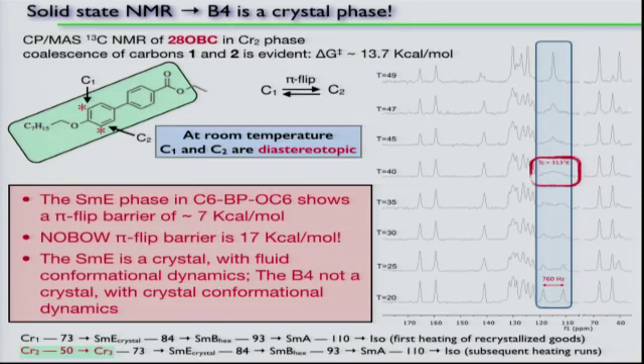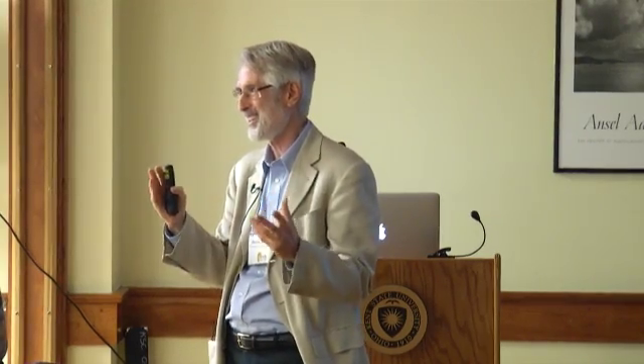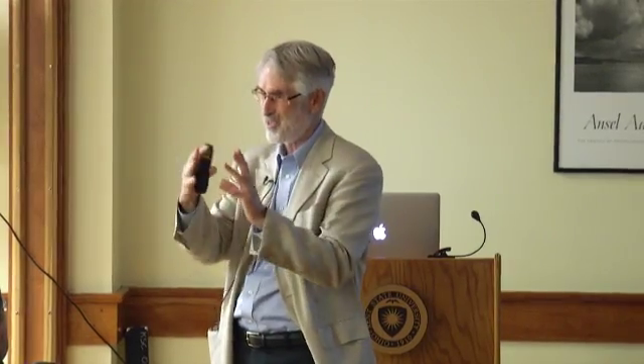And so what you see is you can measure very slow conformational dynamics by solid state NMR. So for example, this is a crystal, this 28 OBC, beautiful mesogen, and has lots of really nice phases, including 3 crystal modifications and a smectic E, smectic B hexatic, smectic A. Okay? And if you look at this stuff in the crystal phase at room temperature, you see that these 2 carbons, okay, I mean, this gets to the diastereomers versus enantiomers thing, and the homomers. Homomers, of course, are congruent. Okay? But it's even more complicated because it's dynamic, right?